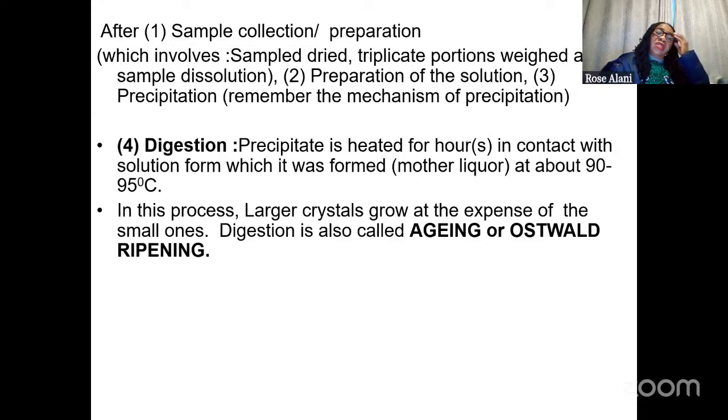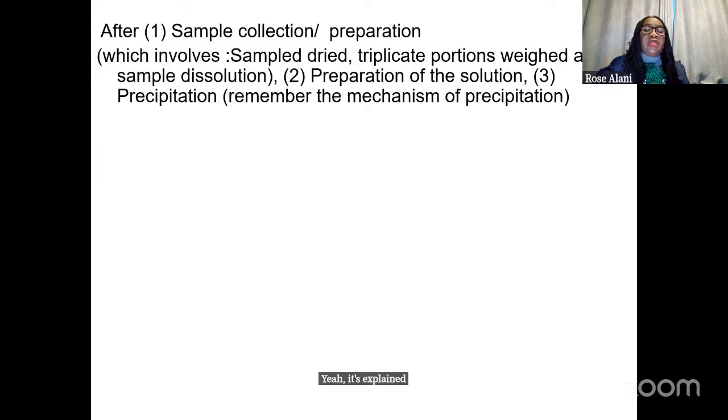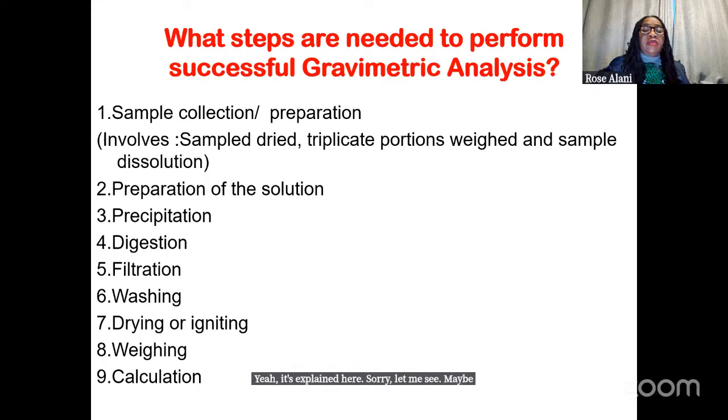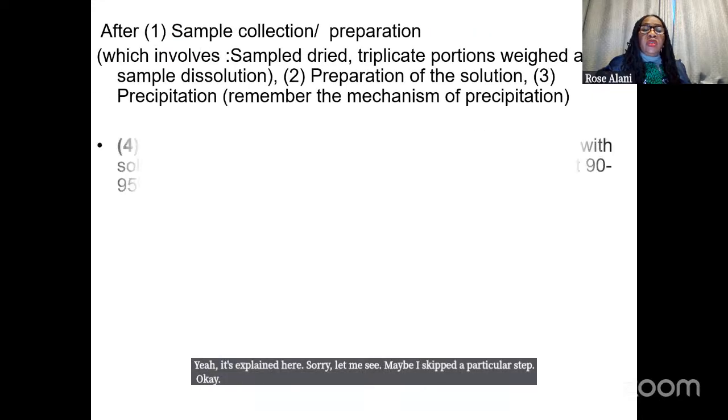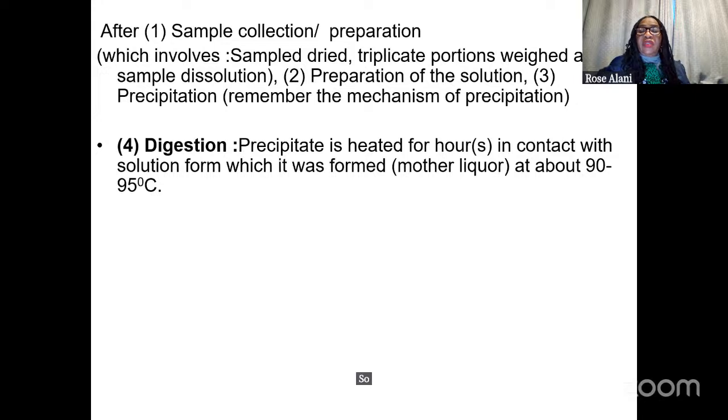So the digestion here is explained here. The digestion is heating your solution in which the precipitate is already present, at about 90 to 95 degrees centigrade.